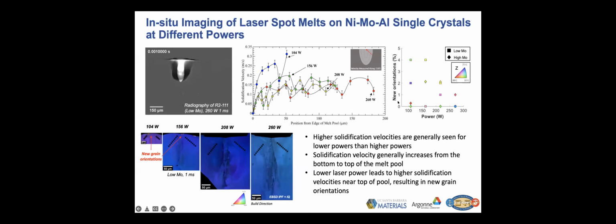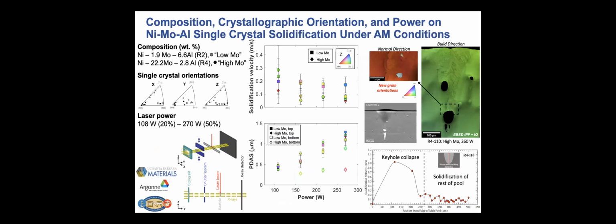Over here on the right, looking at new orientations versus power, again, at the lower power conditions, we tend to see more new orientations towards the tops of the melt pools where the higher velocities are experienced. As I mentioned, we looked at different compositions. These are a couple different alloy compositions we looked at, different single crystal orientations, and different laser power conditions. Here we're looking at solidification velocity versus power. Again, we tend to see higher velocities for lower power conditions.